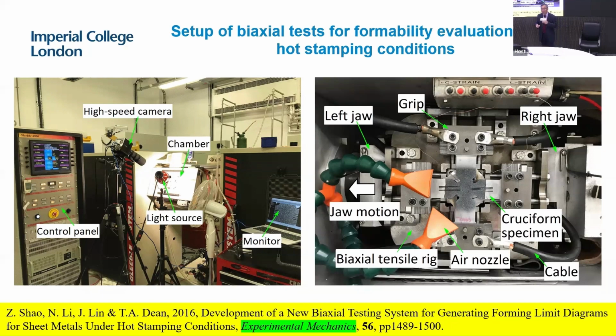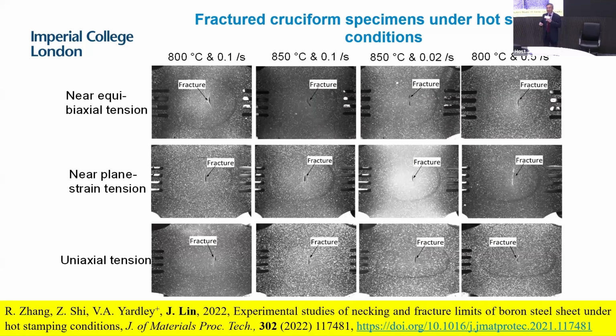And now we try to do the testing for boron steel, which is commonly used for hot stamping. This is a specimen, and we paint it, and I'm not going to discuss this in detail, and probably most people know Gleeble. With the biaxial test rig we developed, patented, and attached to the Gleeble, we did the test at different temperatures and strain rates, and we just show three: near equal biaxial, near plane strain and near uniaxial tension. We can see the failure occurs almost all of them closer to the center of the specimens, which is what we want.